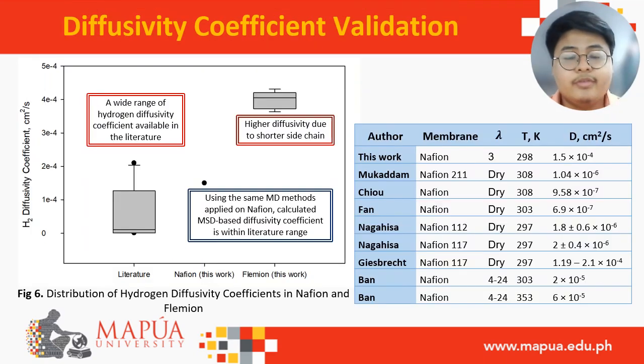To validate our results, we applied the same methodology to Nafion to serve as a comparison, as there is a lack of data available for Flemion for direct comparison. What we have determined from the literature is that there is a wide range of hydrogen diffusivity coefficients available for Nafion. Using the same molecular dynamics methods applied on Nafion, the calculated MSD-based diffusivity coefficient is within the literature range.